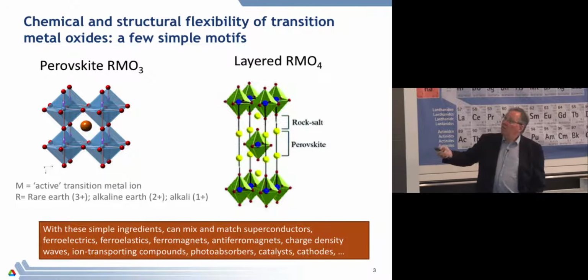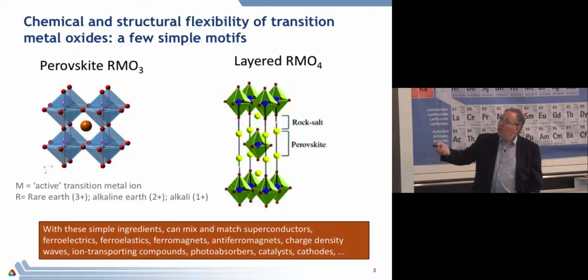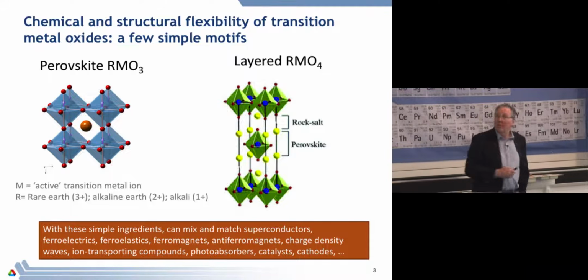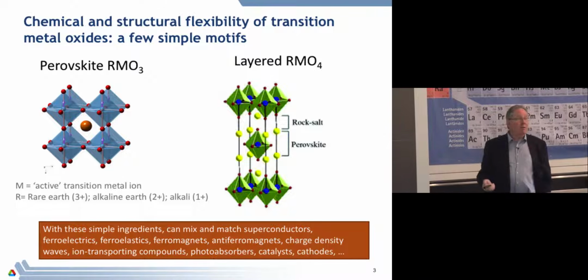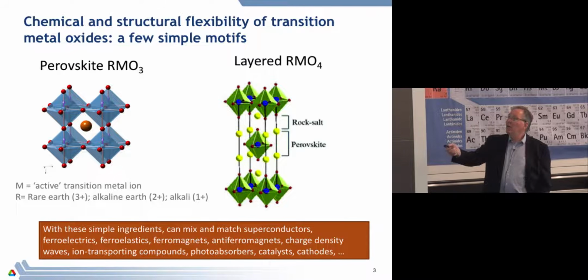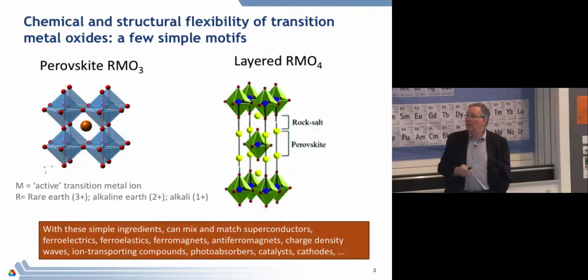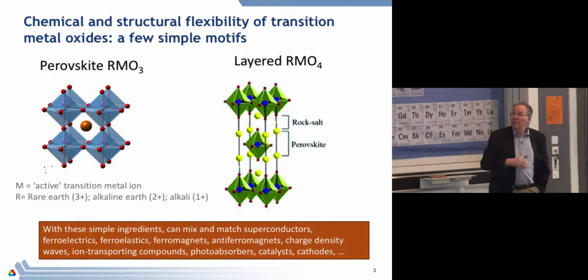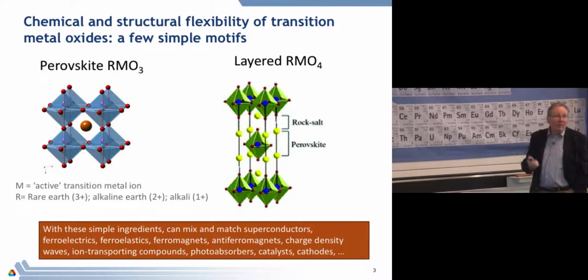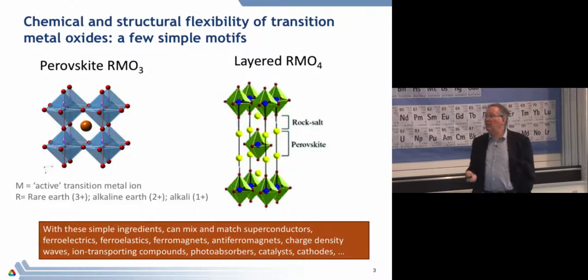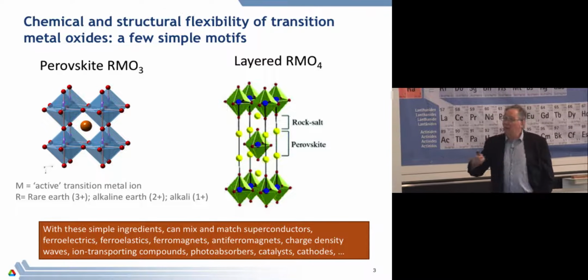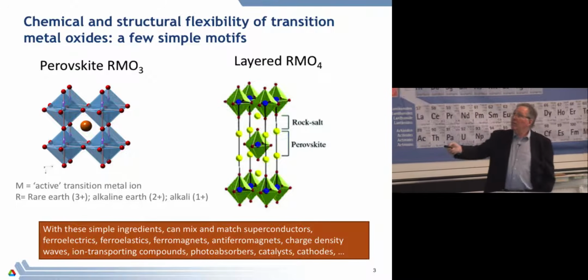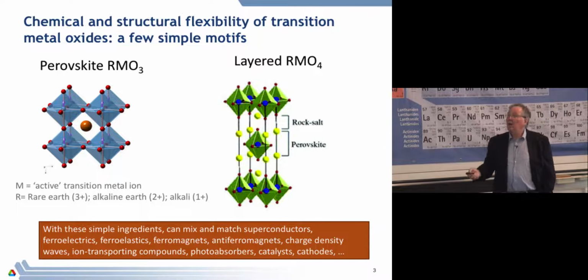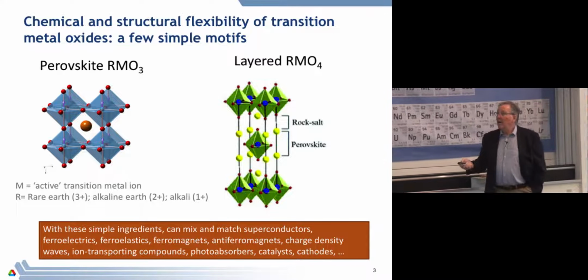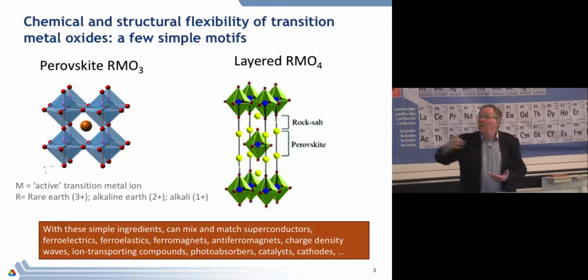And the way that I tune the properties here is by doping, and the doping comes because there's an ion which sits at the center here, which is typically either a rare earth or an alkaline earth or maybe an alkali element. And of course, as I go from 3+ to 2+ to 1+, charges will come off this ion and go onto that. And so that is used to dope these structures. And you have a kind of a mix and match that you can play with this, where you can make superconductors like lanthanum copper oxide, ferroelectrics like barium titanate, ferroelastics, ferromagnets, antiferromagnets, charge density waves, ion transporting materials, because ions which sit in the middle of these cages can move around a lot. They're used to absorb light, to make photoabsorbers, and of course to make catalysts and cathodes. So there's a long array of these things.